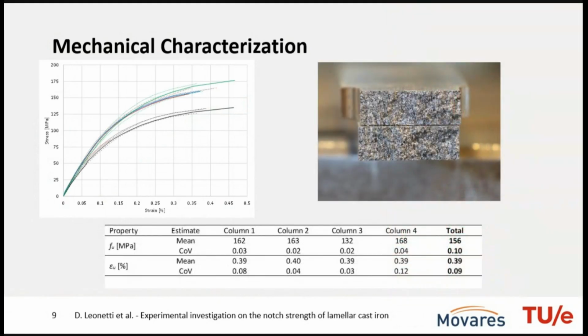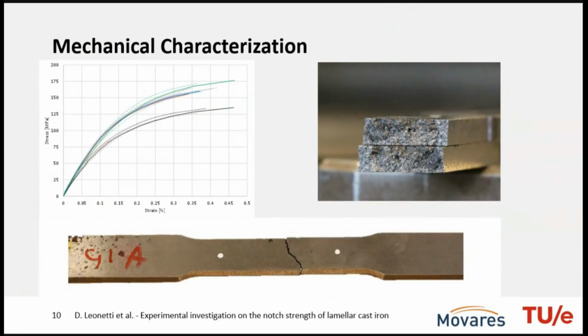When we look at fracture surfaces, if you could test the specimen and you don't find any defect, then you are able to reach about 150 megapascal of ultimate tensile stress, and the fracture surface appears like this, very crystalline, transverse to the loading direction. The material behaves fairly brittle, and there is no sign of necking or yielding, no gross plasticity takes place. But for some specimens here and there, we found the presence of casting defects. You can see here what we think is a shrinkage porosity for a specimen that eventually failed at a lower value of stress as compared to the others.